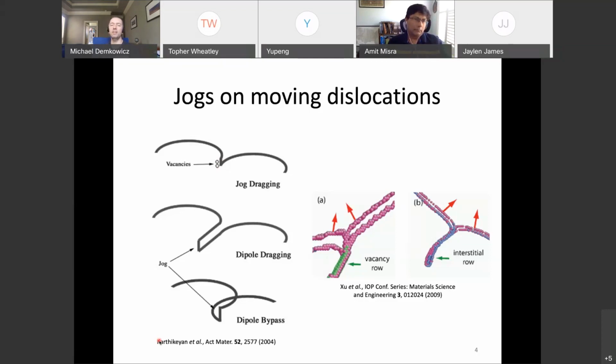You can't affect the rate of diffusion by applying stresses, right? Stresses act directly on dislocations, and they can make dislocations move, but you can't make vacancies move by applying stresses, right? So vacancies are going to move at whatever rate they want to move, and that's really determined mostly by temperature.